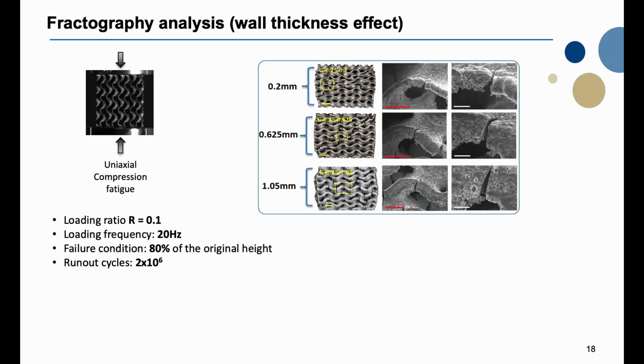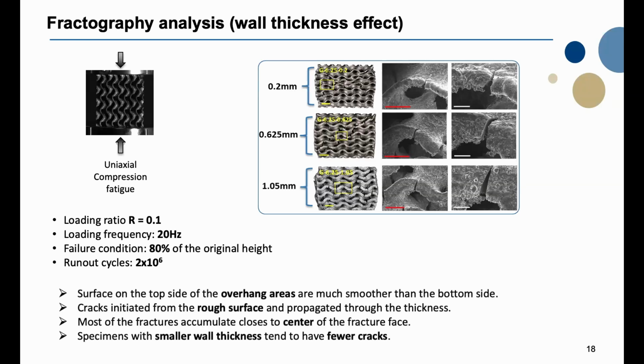And fractography analysis was also performed on the lattices here. And this is for the fatigue loading conditions. The frequency was 20 Hertz, the failure condition was 80% of the original height, and the runout cycle was 2 million. As we can see here, the surface on the top side, which has overhang areas, is much smoother than the bottom side. So depending on the geometry of the specimens, the fabrication quality is really different. The crack initiated from the rough surface and propagated through the thickness. Most of the fractures occur close to the center of the fracture surface. And the specimens with smaller thickness tend to have fewer cracks according to the observations.